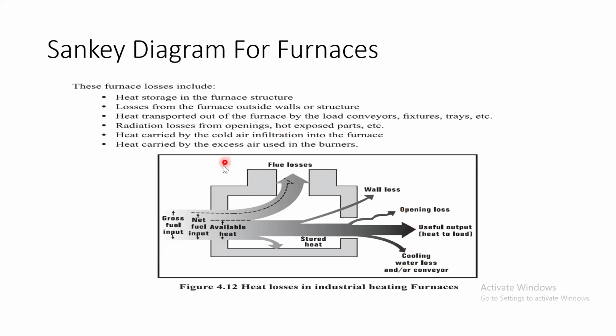Then cooling water loss, because all these components inside the furnace are cooled by circulating cool water, so that the basic parent metals used in and around the furnace do not get damaged immediately, because you are using very high temperatures. So that huge heat has to be removed by cooling water circulation. That water will slightly become hot, and then that hot water will be recycled through the cooling towers. So this is wall loss, opening loss, cooling water loss, and this is the stored heat which goes to the process, and these are all the losses in the furnace. Okay, any doubt?